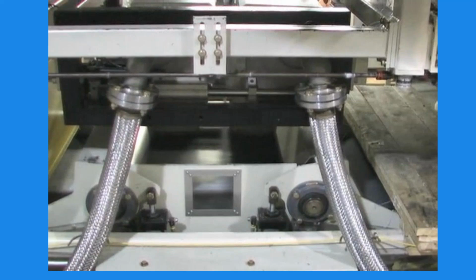A needle punch line is usually a carded web. So you have a randomized short staple fiber that you thicken up to sometimes 100 GSM, 200 GSM, and then you run it through a needle punch machine. A needle punch machine is a very different process than what we've looked at. Imagine a bed of nails with barbs sticking up, special little needles with barbs in different shapes. The needles meet with holes in plates, and there can be as many as 1,000 needles, actually a lot more than that, per meter of width of the line. Those needles go in and out of the fabric at a very rapid rate, and the barbs cause the fibers to wrap around and lock together. That's the way you make felt and some other air filtration media. So I didn't cover it here for PPE, but it is a unique process.